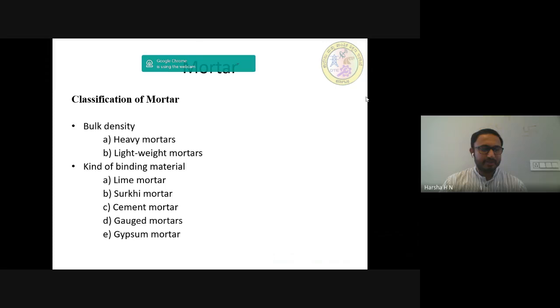Next type of mortar is surki mortar. This type of mortar is prepared by using fully surki instead of sand or by replacing half of sand in lime mortar. The powder of surki should be fine enough to pass BIS number 9 sieve and the residue should not be more than 10% by weight. The surki mortar is used for ordinary masonry works of all kinds in foundation and superstructure. But it cannot be used for plastering or pointing works since surki is likely to disintegrate after some time.